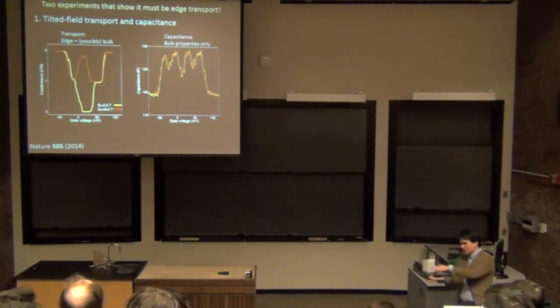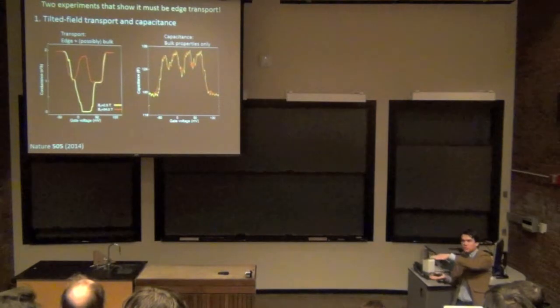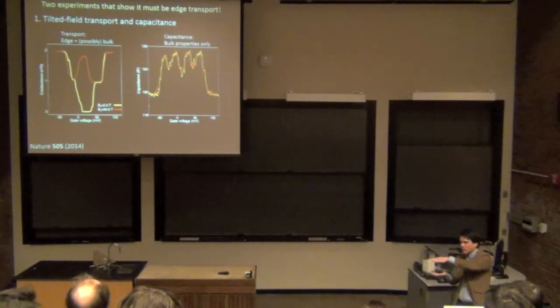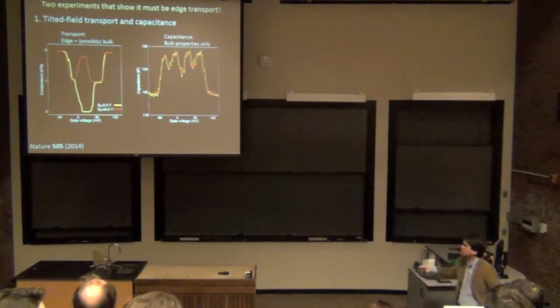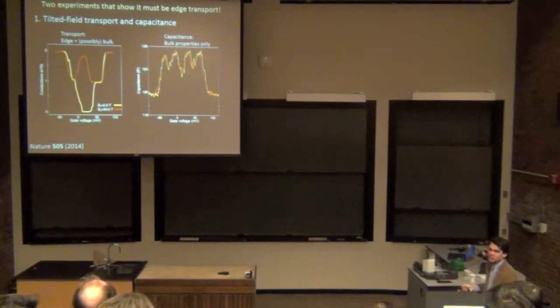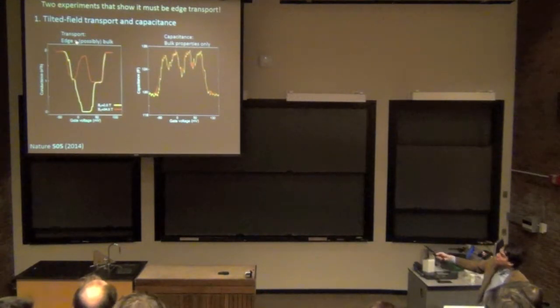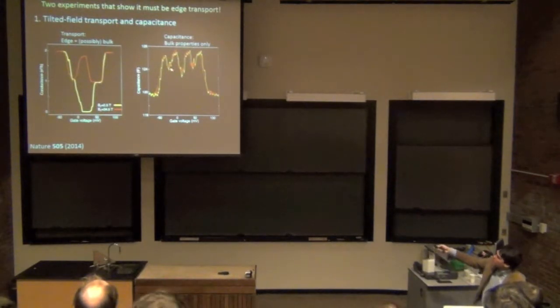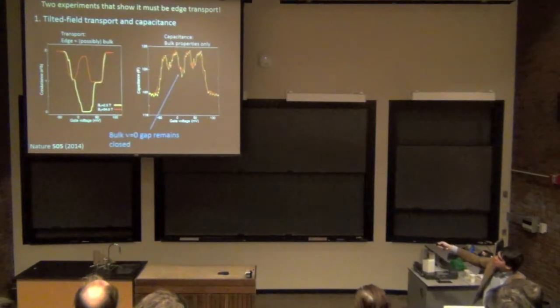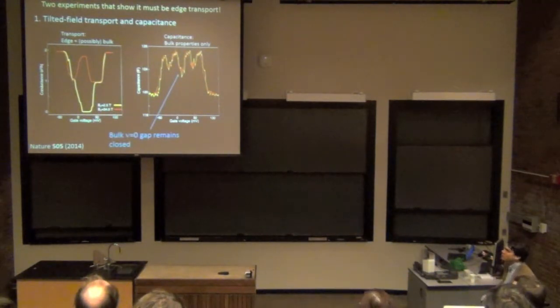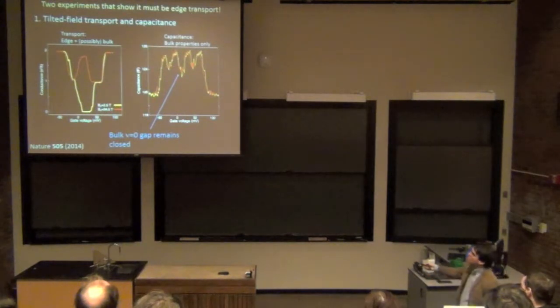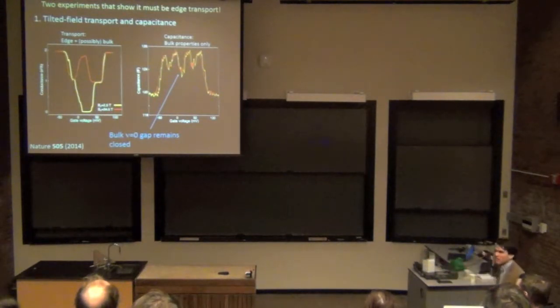Capacitance, on the other hand, basically just measures the charging between the graphene layer and the adjacent layer, which tells you about the bulk properties of the system, right? So here we're seeing an immense change in the conduction properties, but we measure the capacitance in tilted field as well, and we see that this bulk gap, the dip in the density of states, remains closed. So that's one piece of evidence that this transition is happening along the edges of the sample.